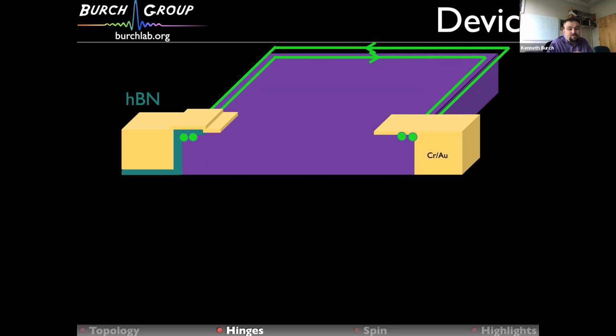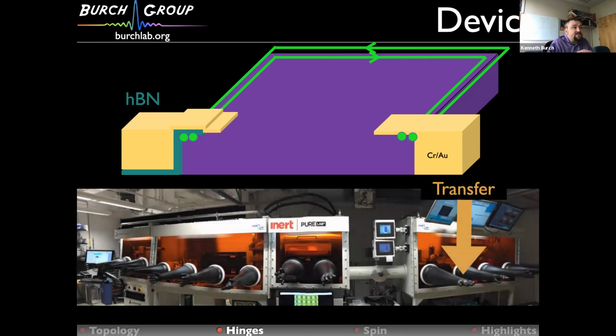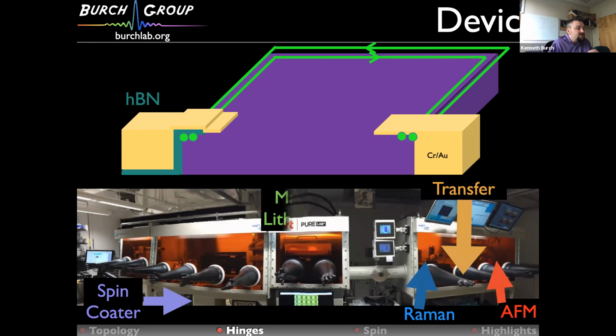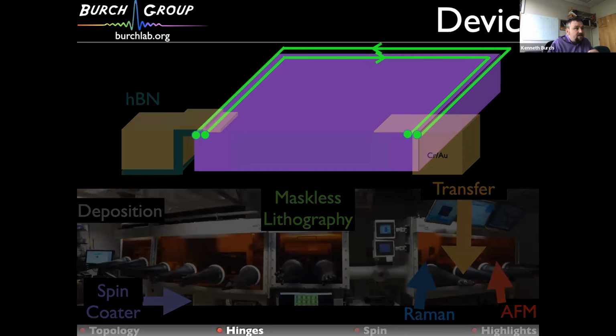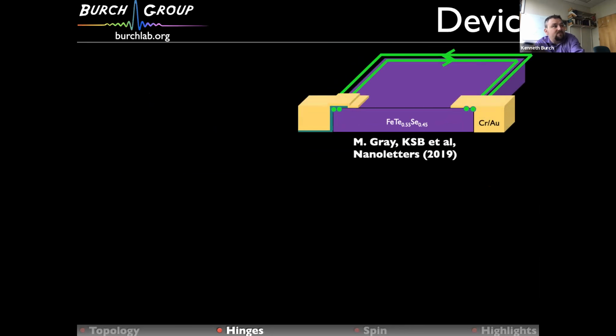And we did all of this inside of our clean room in a glove box, which is what allows us to do all this very fast and with air sensitive material. So we can do 2D transfer like others. We have Raman and AFM inside. So by the way, if you have air sensitive materials, we can help. And then we have a spin coater, a maskless lithography, and a deposition tool. Okay, enough with the shameless self-promotion of our toys.